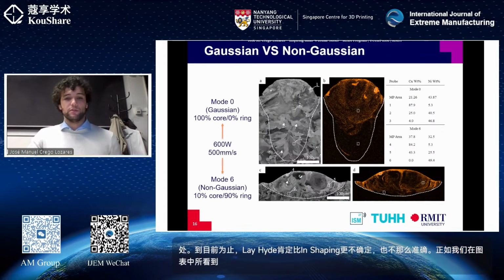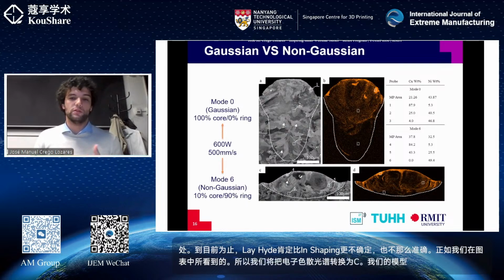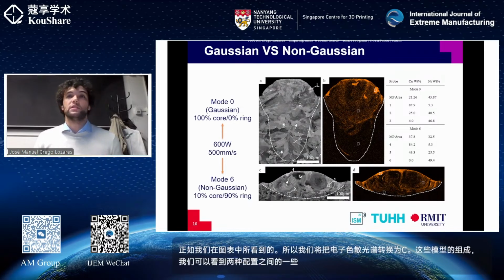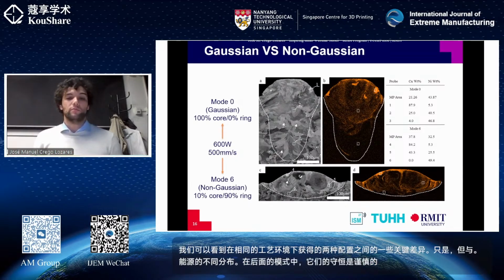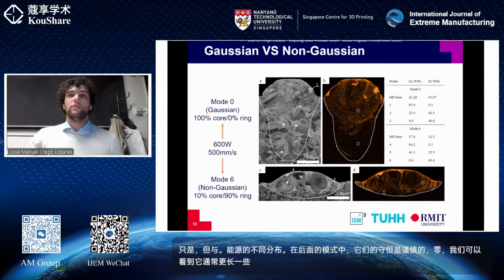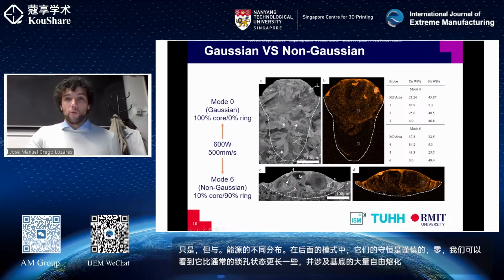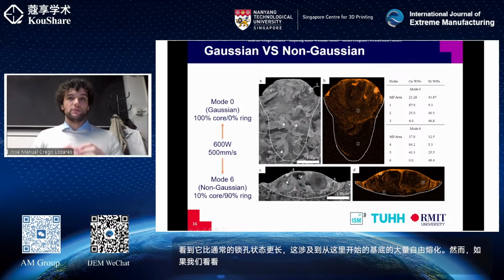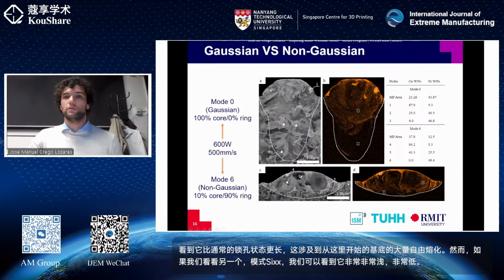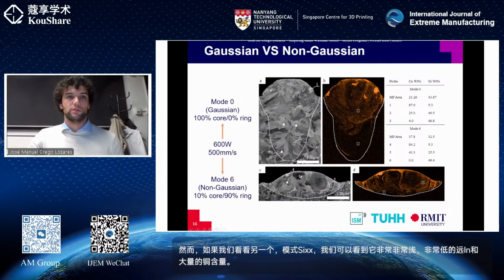If we use energy dispersive spectroscopy to see the composition of the melt pool, we can see some key differences between the two configurations obtained for the same processing parameters, but with different distribution of the energy source. The configuration obtained with Gaussian, in laser mode 0, is a bit more elongated, typical of keyhole regime, and involves a lot of remelting of the substrate, starting here. However, if we look at the other one, mode 6, we can see that it's very, very shallow, with very low remelting, and a lot of copper content, very much closer to the original substrate start.